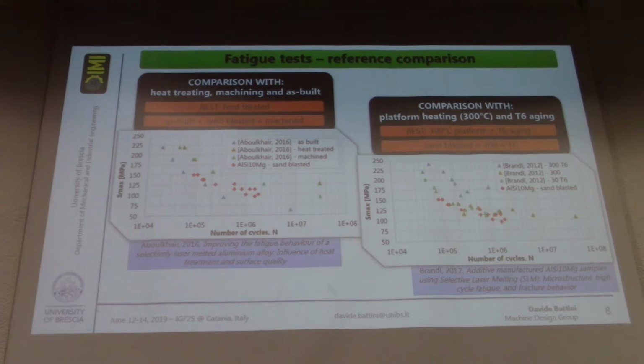As comparison to some literature data, our specimens behave better, as we can see here, than as-built specimens, but of course worse than specimens that were post-treated with more expensive post-treatments like machining or ad hoc heat treatment. The performance were actually pretty comparable with aged specimens or preheated bed machined specimens, but when combining the preheating and the aging, specimens are actually performing a lot better.